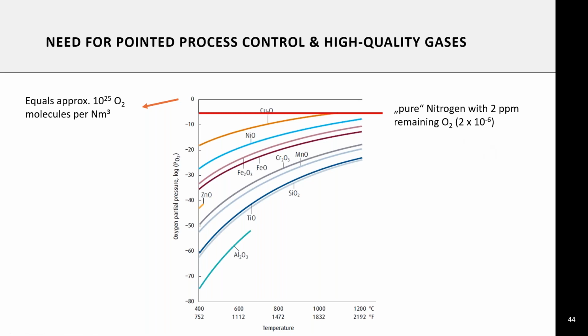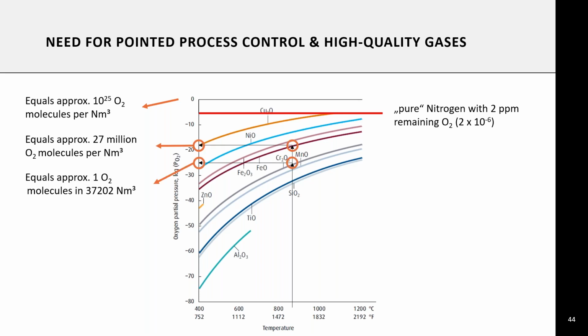The nitrogen, an oxygen partial pressure at 0 equals roughly 10 to the 25th power oxygen molecules per cubic meter. Nitrogen with 2 parts per million remaining oxygen, which is 5.0 purity from the description in the previous slide, will oxidize all metals.